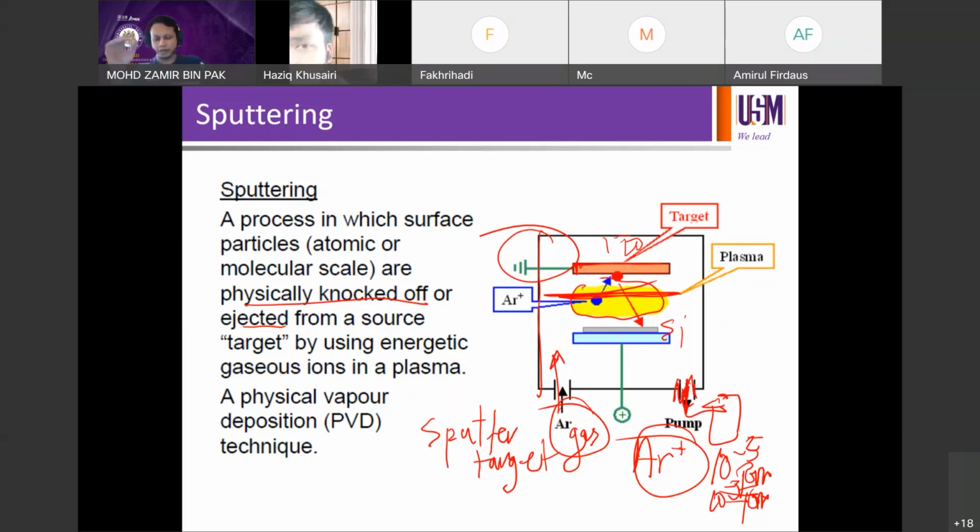So when I was in the R&D team, to be able to create the layer to store the data, however many megabytes, terabytes or gigabytes, you have to sputter 20 plus magnetic layers. Very thin ones, only tens of nanometers per layer, but multiple layers, like 20 layers or so.